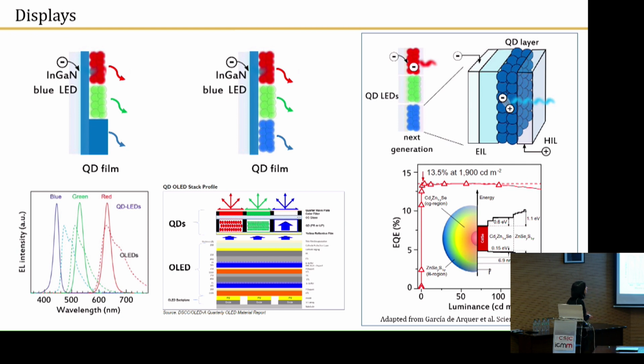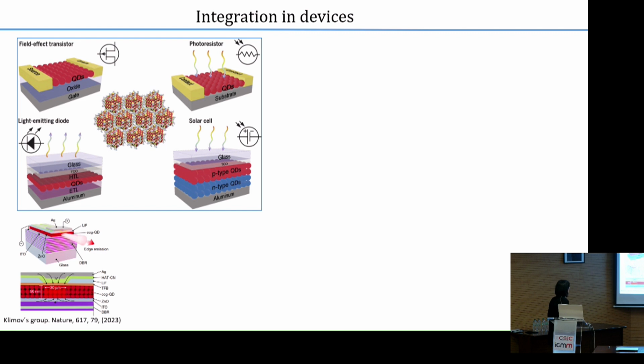These are the mechanisms in which the PL drops because of this way to relax. So the next generation will be composed, as far as I understand, of these graded shells surrounding quantum dots. By exploring these systems, it's feasible that the next generation will be successful in this respect, with electrically excited quantum dots. Indeed, this year, the group of Klimov already published a paper in which quantum dots can be electrically excited to produce an electrically excited laser.